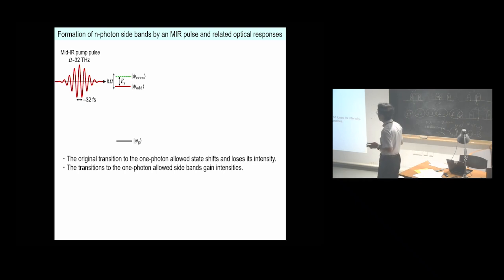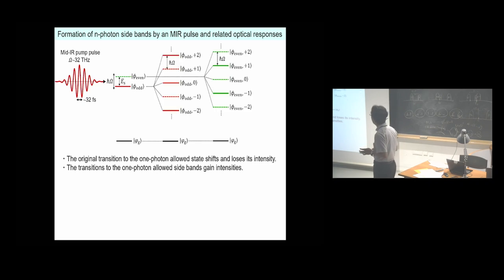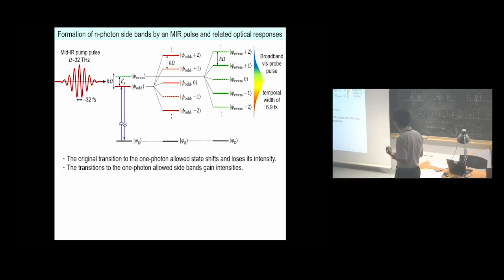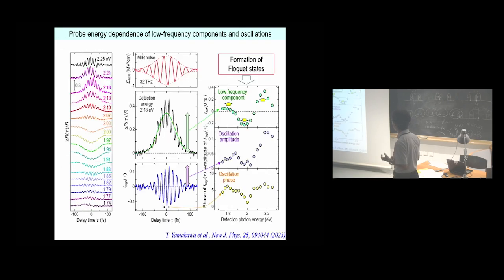By the mid-infrared electric field, the n-photon sidebands are created around the original odd parity and even parity states. The solid lines show the one-photon allowed states. When a broadband probe pulse is incident here, the original transition to the one-photon allowed state shown here shifts and loses its intensity in this state. In addition, the transitions to the one-photon allowed sidebands shown here gain intensity. These responses should be reflected by this spectrum of the low frequency component.